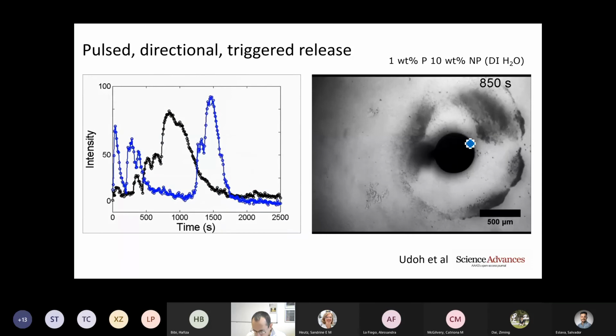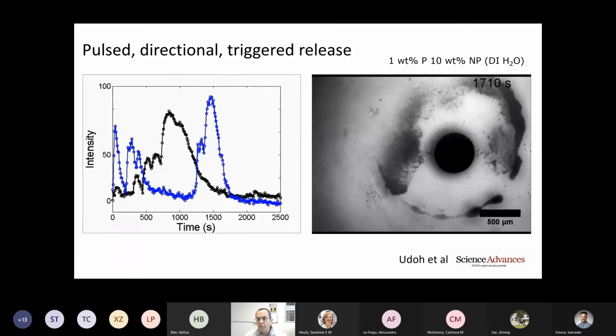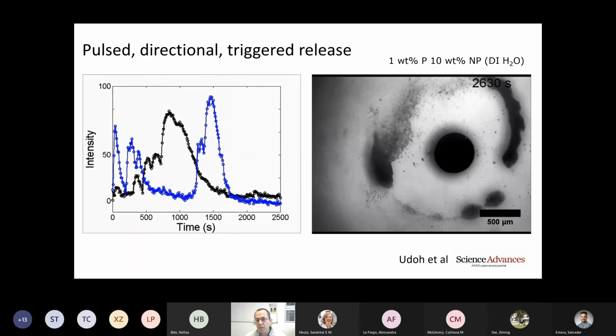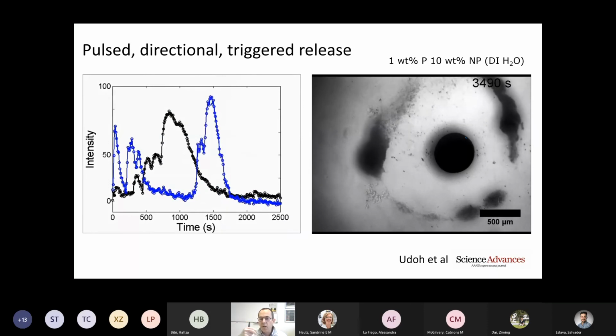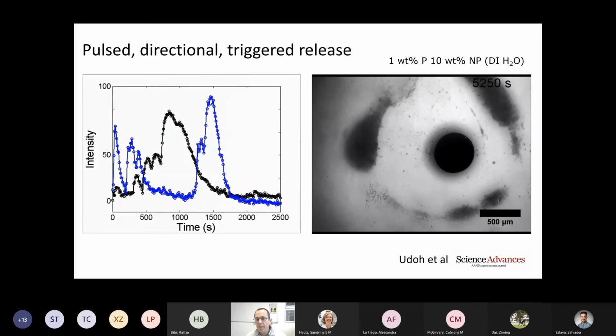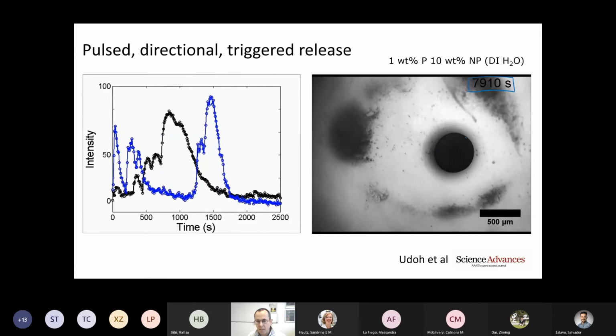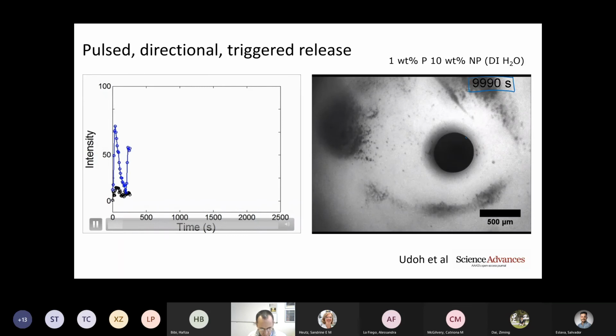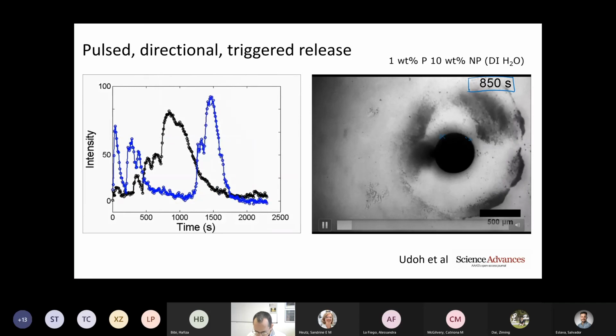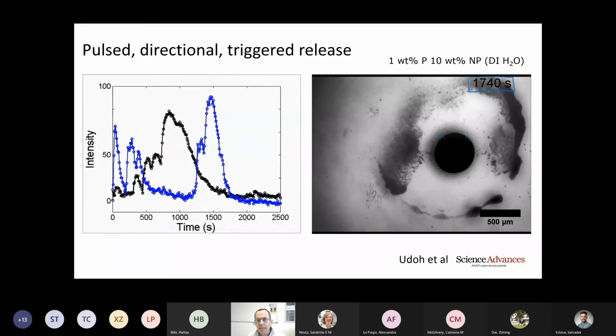You have these compartments that explode like volcanoes because we've created pockets of high osmotic pressure that, once embedded within a good solvent, will explode in this compartmentalized way. You can induce active particles in this way, but significantly the timescales for this are huge and orders of magnitude longer compared to the timescales of the dissolution of just the polymer itself, which is a water-soluble polymer that will dissolve within some tens of seconds for these dimensions. And here on the left, you see a concentration profile that corresponds to a couple of points within this, over here and here, that correspond to two points of the dissolution of this particle.